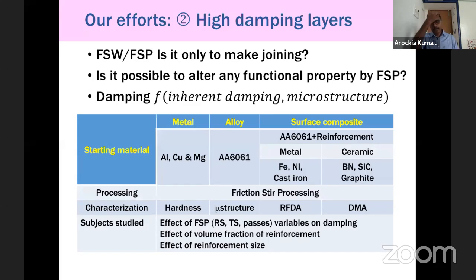What we have done is process aluminum, copper and magnesium metals, and we have also chosen some aluminum alloy, 6061, and prepared some surface composites. Then we characterized the damping property using a dynamic mechanical analyzer, and a technique called impulse excitation technique, or resonant frequency damping analyzer. Using these two techniques, we analyzed the damping property of our FSP materials.